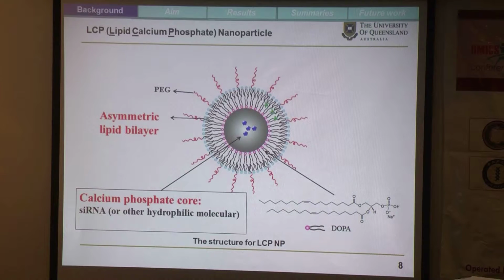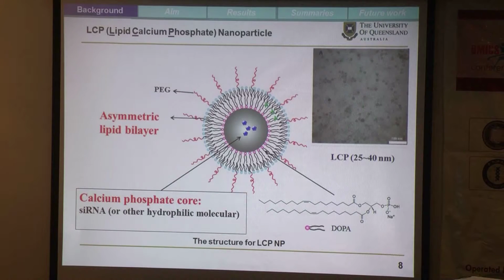And as we know, the pure small liposome size is from 50 to 100 nanometers. But in our case, the size of the LCP nanoparticles can be reduced to about 30 nanometers. So we can emphasize that the size of the LCP nanoparticle is predominantly dependent on the inner calcium phosphate core.